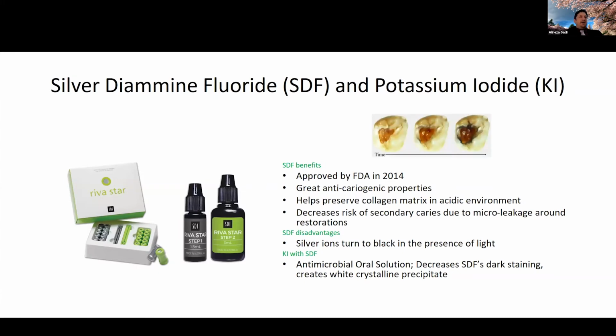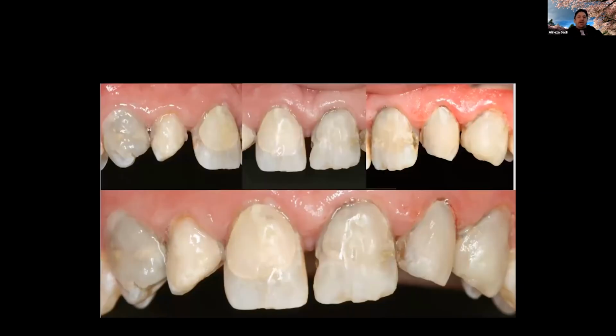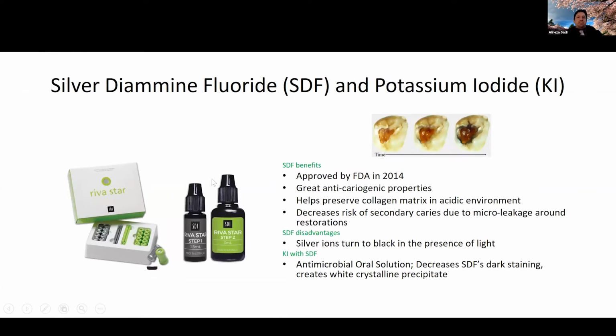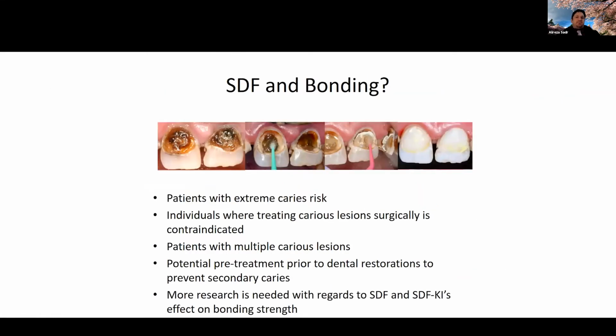Now, people ask, so here is the discoloration that you could expect from SDF. People ask, if we don't have Riva Star, are there ways that we can decrease the discoloration? Yes, you could use your silver diamine fluoride and get a potassium iodide from a different source. Now, there is potassium iodide sold in pharmacies and all that. So I can't really recommend that, but that is one approach to reduce the SDF staining if you don't have access to Riva Star. But Riva Star is, of course, a system that has SDF as one step and potassium iodide as a second step.